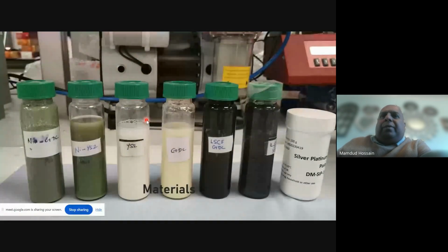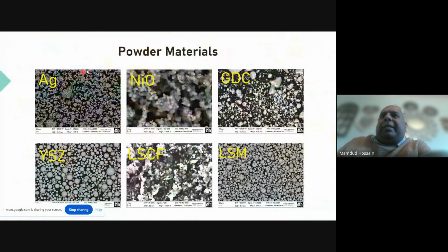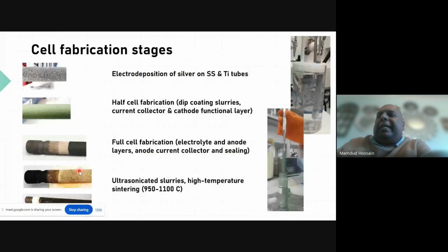Okay, so what are the materials we bought? We bought nickel oxide GDC slurry here, nickel YSZ again slurry, YSZ slurry, GDC, LSCF GDC. We mixed it up. We went through a lot of ball milling and this and that system. Then we looked at the powder material. We looked at the microstructure to give us some sense of what type of material we are dealing with, and then we started layering on top of each other.